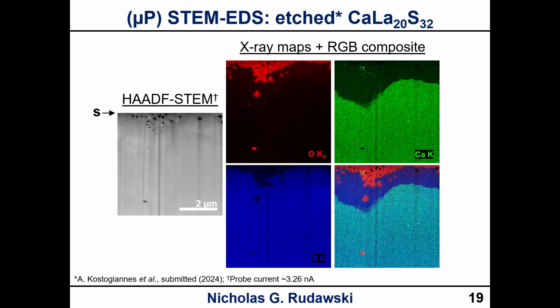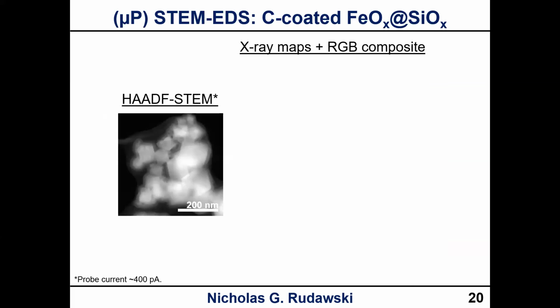Okay. So again, this is fairly coarse scale, right, as far as STEM is concerned. And this was done with a really large probe current. Okay. So several nanoamps. Okay. But getting really nice maps here, great signal, and there's no reason why you wouldn't want to do this at this kind of scale.